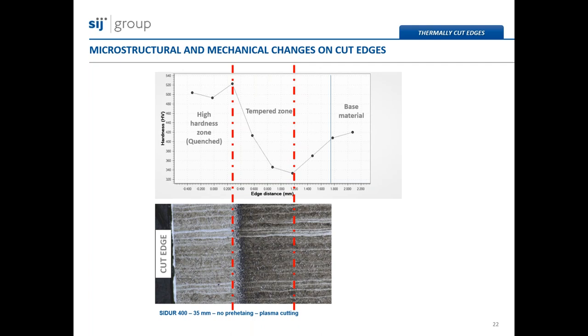The next region, between both red lines, is the so-called tempered zone. This zone has much lower hardness, but in this region we detect a high deviation of hardness, where the minimum is at approximately 340 Vickers. From this zone, the hardness rises to the base metal level of approximately 400 Vickers.